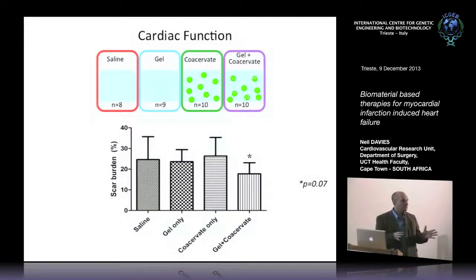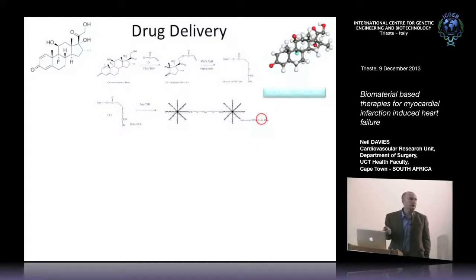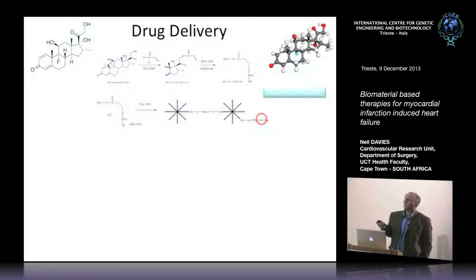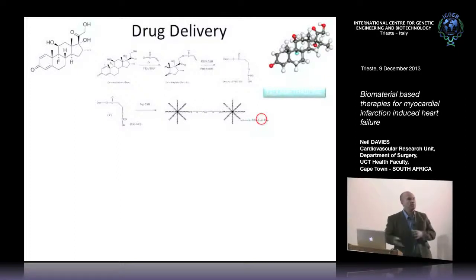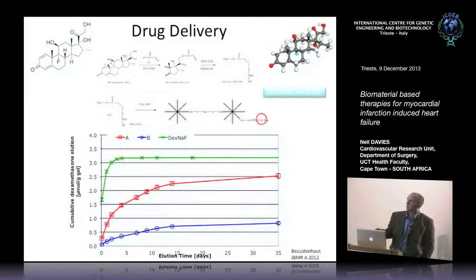Our hydrogel is a platform for a variety of ways of targeting the heart. Any drug with a hydroxyl group — for instance dexamethasone, which has quite a number of hydroxyls — can be coupled via an acrylate to our hydrogel, then hydrolytically released in a completely unmodified form. The dexamethasone can essentially be pegylated, attached to our hydrogel, and released unmodified. We can control the release rate in vitro using slightly different chemistries.